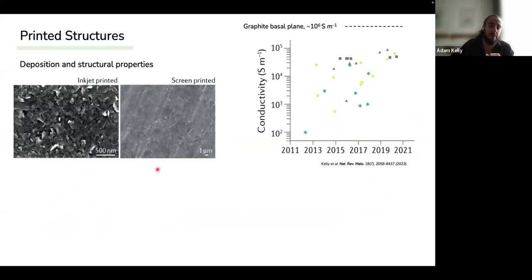So we printed these materials. What do the networks look like? Well, we've an inkjet printed network here. What we can see is the nanosheets are quite obvious. There's quite a lot of holes in here as well. The porosity is quite high. And if you look at a screen printed network, it's very, very hard to see the nanosheets. Okay, so the deposition method clearly has an effect on the structure of the network itself.